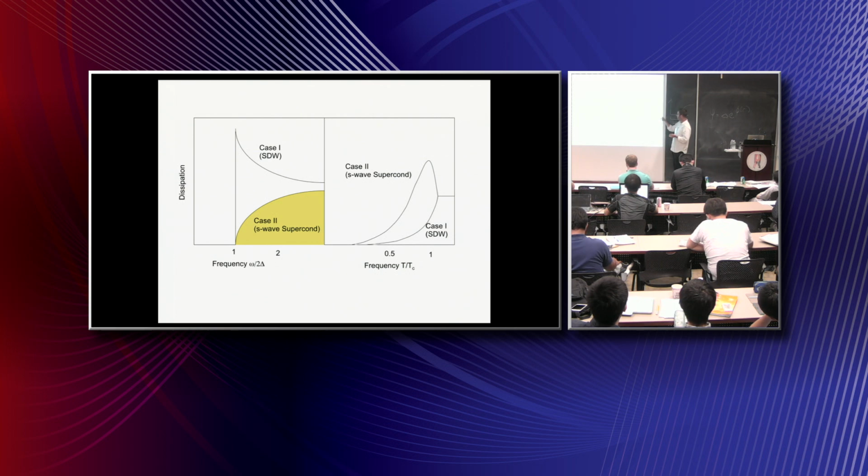As a function of temperature, you'll see just the opposite: there's a big peak here, just below Tc. When this was measured, it was one of the first non-trivial verifications of the BCS theory of superconductivity. When they did NMR relaxation experiments on conventional superconductors, done in Illinois by Hebel and Slichter in the 1950s, it was found in the NMR susceptibility experiments that there was a large peak just below Tc. I've drawn it here as a cartoon, but the real data looks very similar.